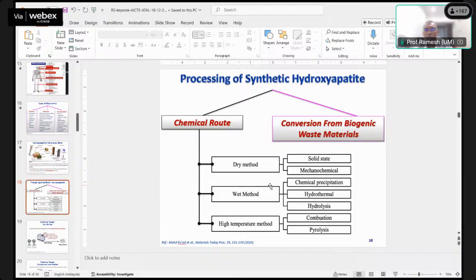The wet method, as the name implies, is done under wet conditions. So normally the famous one is chemical precipitation, where we react calcium-based material in a liquid form with a phosphate-based component also in a liquid form. So we mix them based on some process, and the yield will be hydroxyapatite. Okay, there is the hydrothermal technique, and there is the hydrolysis technique. Among these three techniques, chemical precipitation allows the researcher to develop a large amount of yield as compared to hydrothermal and hydrolysis. And then of course we have the high temperature method, which is combustion or pyrolysis.